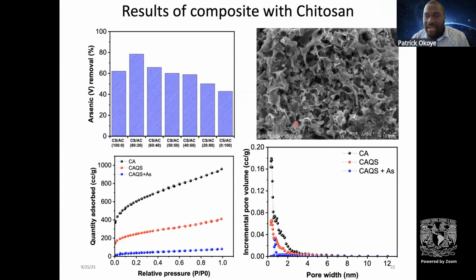Our results were also very fascinating because we have very rich porous materials that were able to remove up to about 79% of arsenic. And what we used was arsenic 5.